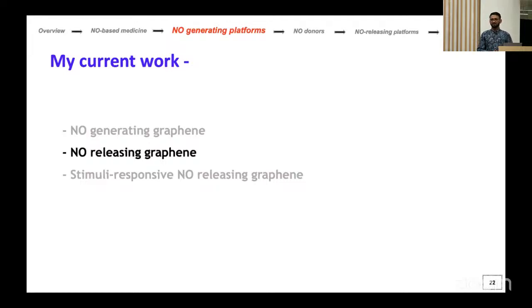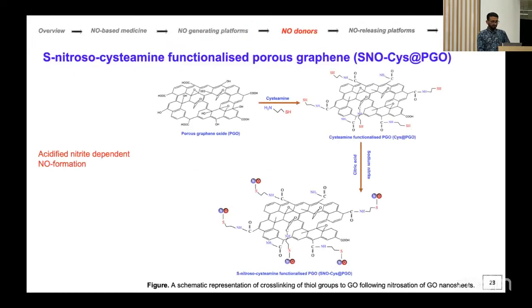They're not using any targeting approach, while we are using ROS responsive, reactive oxygen species responsive nitric oxide, which is directly targeting mitochondria. So this is based on acidified nitrite. First of all, this is a porous graphene oxide, which has pores. We introduce pores into graphene so it can carry more molecules, gases. Then we conjugate it with cysteamine, which has thiol groups. And then those thiol groups have been conjugated to acidified sodium nitrite under acidic conditions. So then we call it S-nitroso-cysteamine functionalized graphene.